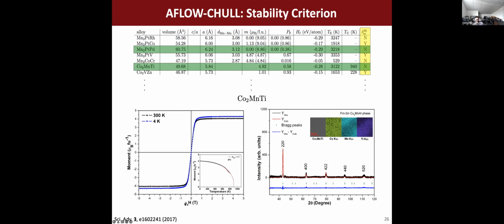And these are the experimental results for this system here, which is really robustly stable. You can see that this system is ferromagnetic, and we can even tell what the Curie temperature is. It's about 950 degrees, which from additional analysis in the paper, we actually did a good job of predicting. And from the XRD analysis, you can see that the system sits on this FCC structure, which is exactly how we predicted the system would form. So it did indeed form this Heusler structure that we predicted. All right, so that's another way that you can use data from the convex hull to do materials discovery.